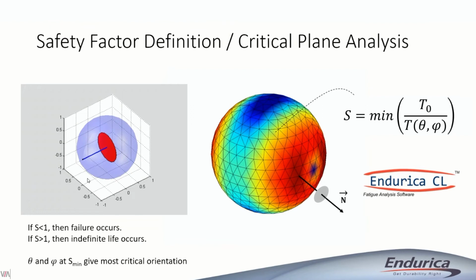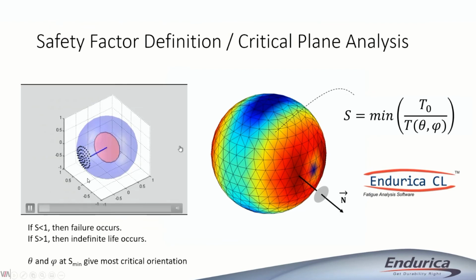And the analysis is actually very simple. We're just going to compute the ratio of the threshold to the energy release rate that occurs for a crack in your material, in your application. Now, of course, the question then becomes, well, which crack? So what we do in analysis here is we look at if you build a finite element model of your part, you can look in the results for each element of your model. And in each element, you could say that the crack might take any of a number of possible orientations.